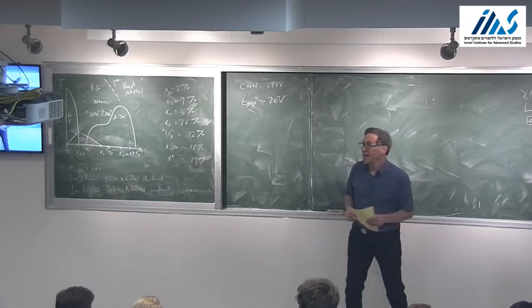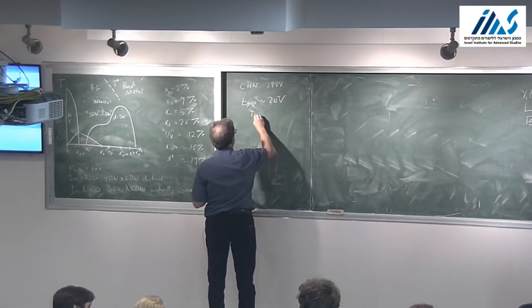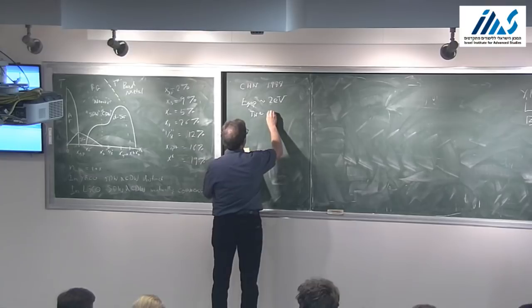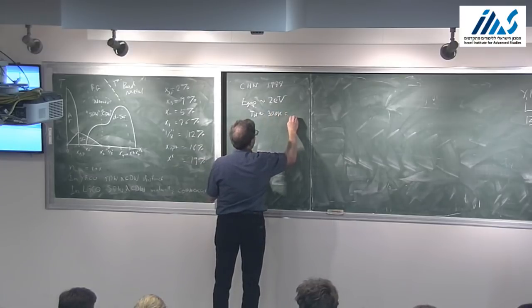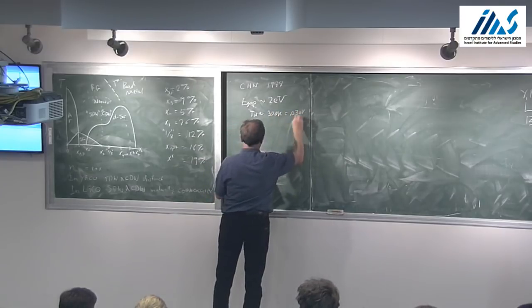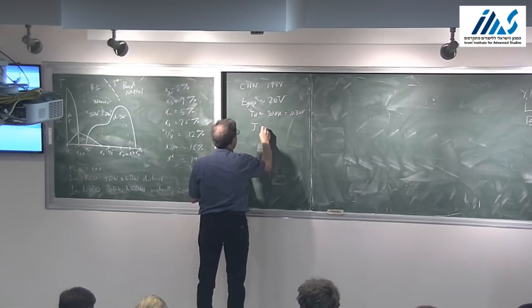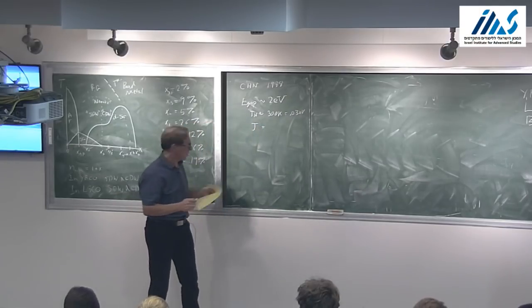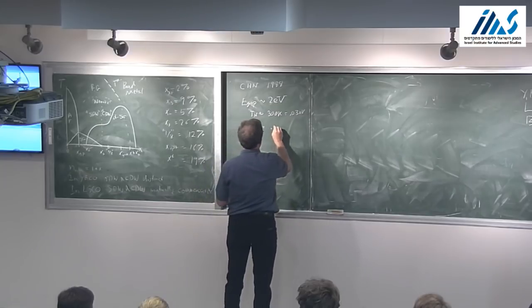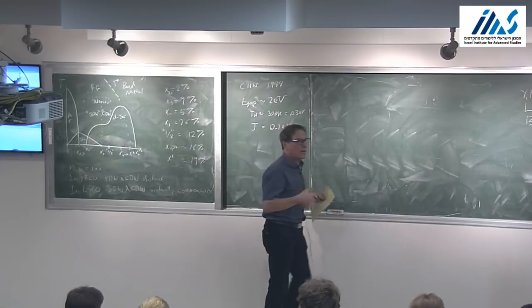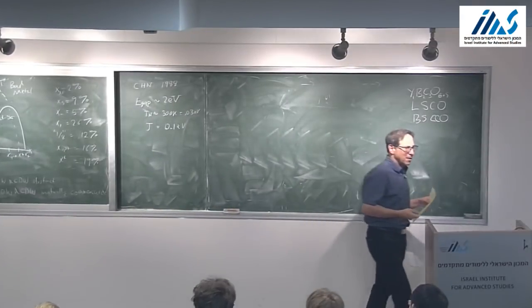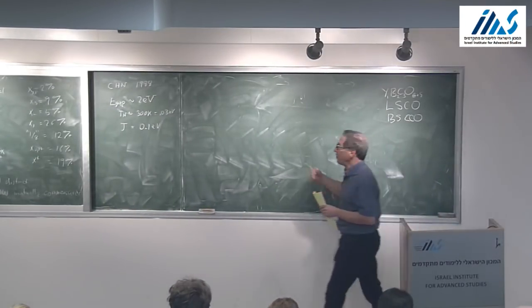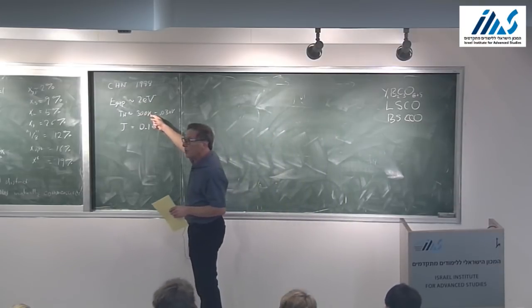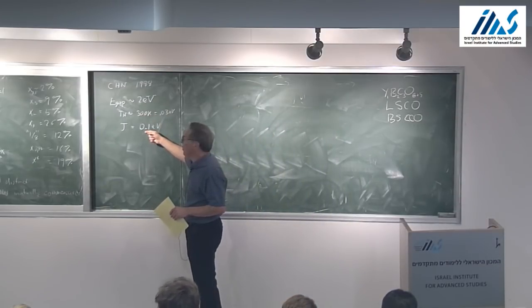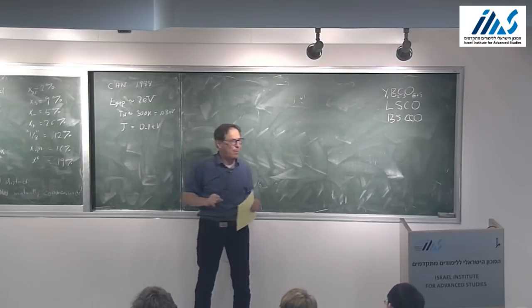Now, the Néel temperature is something like 300 Kelvin, which is 0.03 eV. And J, the antiferromagnetic exchange, which I'll talk about in a minute, is something like 0.1 eV. And what you notice is that these scales, the scale at which magnetic order develops or even starts to develop, are very small compared to this gap.